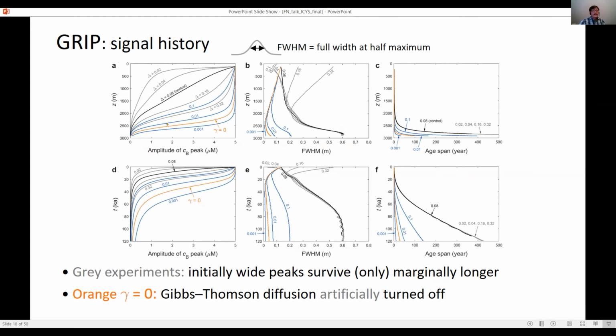But it doesn't survive the residual diffusion down here. This is with the Gibbs-Thomson effect switched off, which is not physical because it's really there. This really just shows the difference between Rampel's theory and the theory where we have all processes. We try injecting narrower peaks and wider peaks, as wide as 32 centimeters under the firn, very wide. And such a wide peak still survives only marginally longer. It gets killed at about 2 kilometers down when the age is only 30,000 years at GRIP. I won't talk too much about the width evolution, but it's essentially controlled by the competition between diffusion and compression.